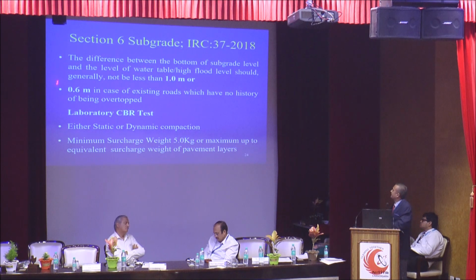In section 6, subgrade: the difference between the bottom of the subgrade level and the level of the high flood water table should generally be not less than 1 meter. If there is an existing road and no overtopping is reported, it can be 0.6 meter. For the laboratory CBR test, though IRC 37 recommends static compaction, we are designing the pavement considering effective resilient modulus of subgrade, which is obtained by correlating CBR with MR value, and that correlation itself has been developed with dynamic loading conditions. So for the laboratory CBR test, it can be either static or dynamic, it doesn't matter.